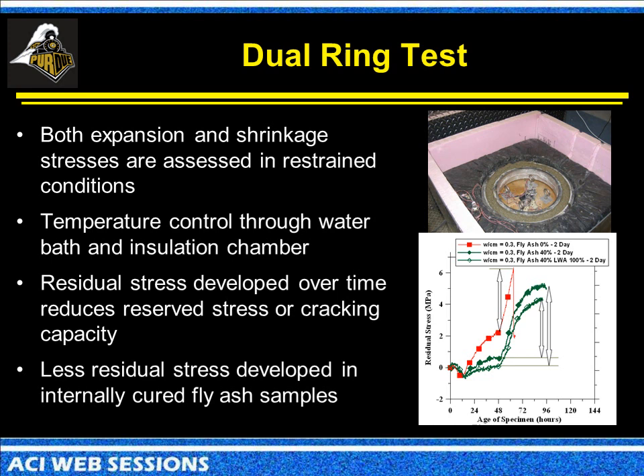We're using INVAR. And the basic idea here, as you can see in this plot, we've got the age of the specimen plotted along the x-axis. We have the stresses that develop inside of the system plotted along the y-axis. And if we just looked at a 0.3 water to cement ratio, we essentially have autogenous stress developing in the system. And after 2 days, what we did was we subjected it to a temperature change. So we said, let's drop the temperature 10 degrees. By dropping the temperature 10 degrees, the stresses went up in the system, and it was enough to crack the overall rings.